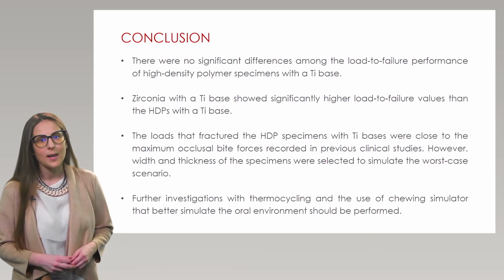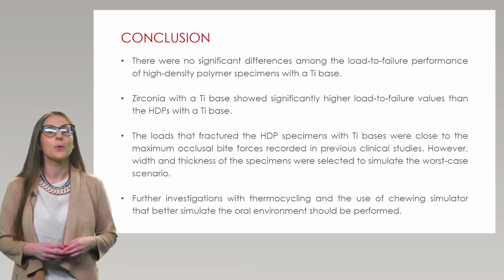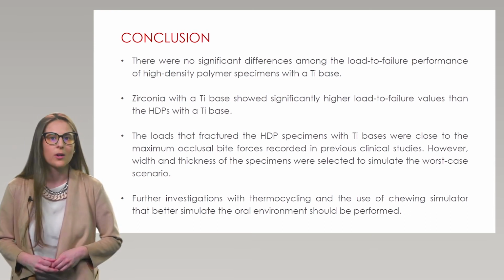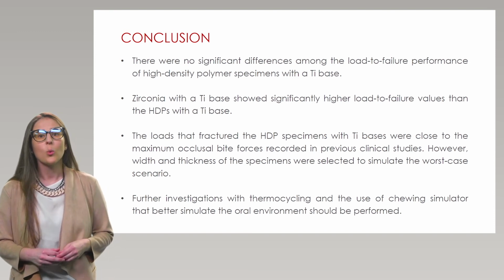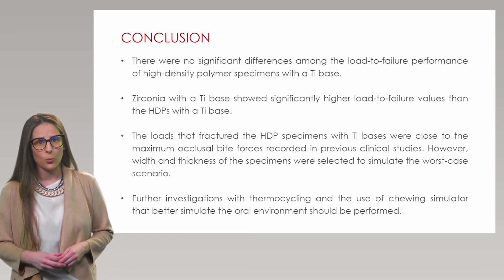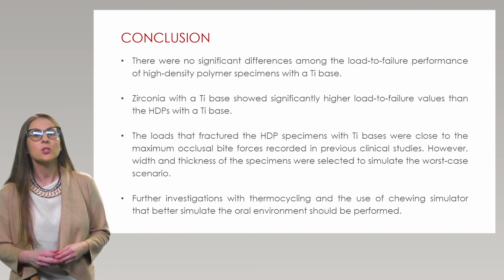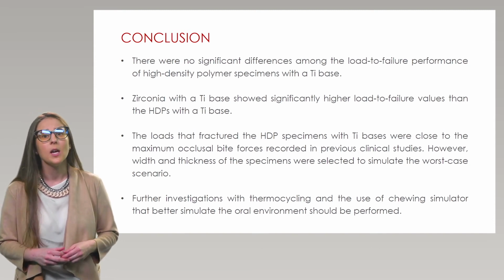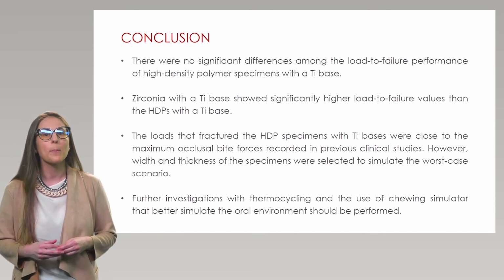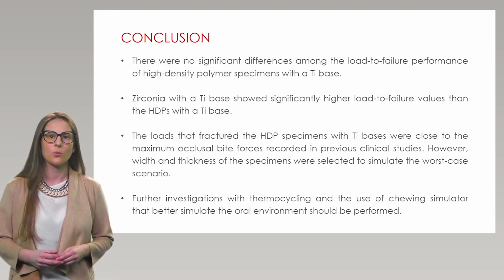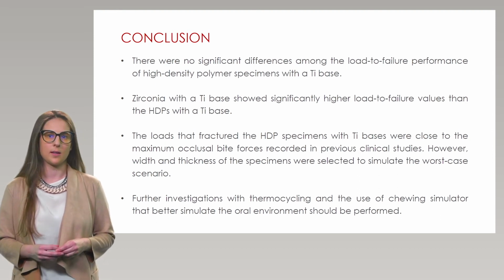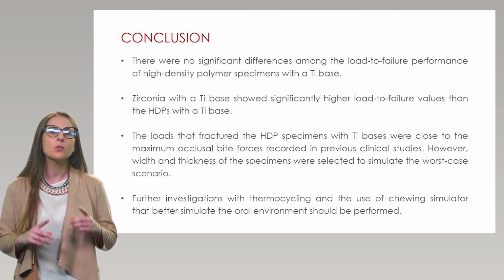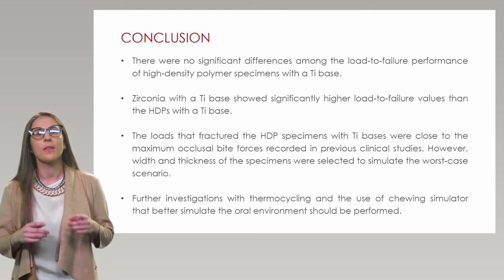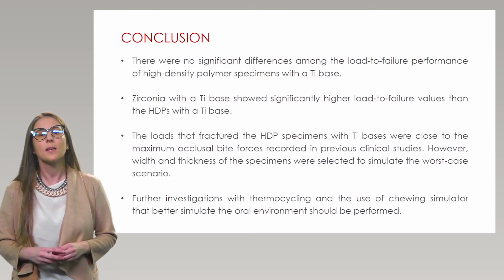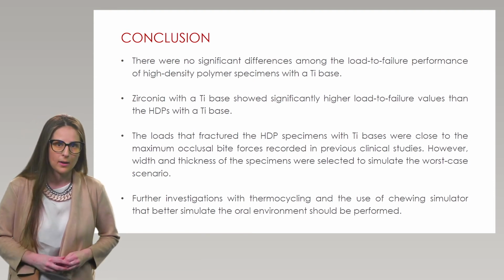All the tested high-density polymer sample presented a similar load to failure performances, lower than what observed in the zirconia group. The loads that fractured the high-density polymer specimen with Ti bases were closer to the maximum occlusal bite forces recorded in previous clinical studies. However, we have to take into consideration that the width and the thickness of the specimen were selected to simulate the worst-case scenario.